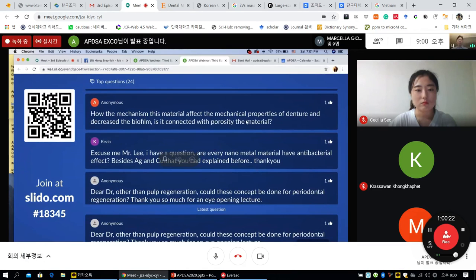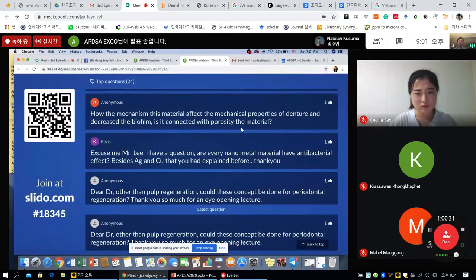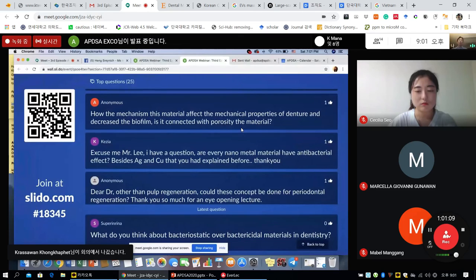How does the mechanism of this material affect the mechanical property of denture and decrease biofilm? Yeah, actually, this nanoparticle has little porosity. So like you said, this porosity can induce some decrease of mechanical property. But I optimized up to 5%, and this amount of nanoparticle does not decrease the mechanical property, so I used that amount. And the biofilm decrease comes from hydrophilicity. Denture resin is hydrophobic, which means when you put water on it, it makes a round shape. But when I added nanoparticle in the denture and added water, the water spreads out, which means it is more hydrophilic. Normally people say that when a material is hydrophilic, it has some anti-biofilm formation. And the second is that if you load silver, silver is the best element to decrease bacteria.